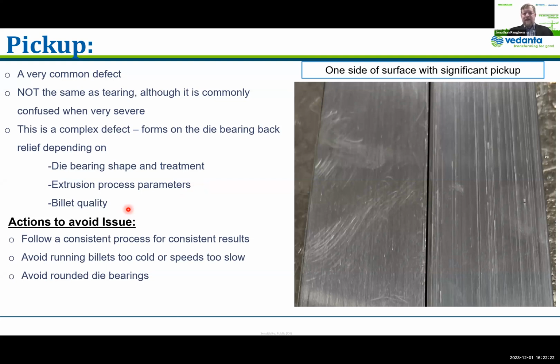These days, the process control has gotten quite good for billet. Generally speaking, it's not a problem, but if there are problems, particularly with homogenization, it can result in a contribution to pickup. So really, and I'll say this multiple times through this talk, if you want consistent results, you need to have a consistent process, and pickup is certainly that.